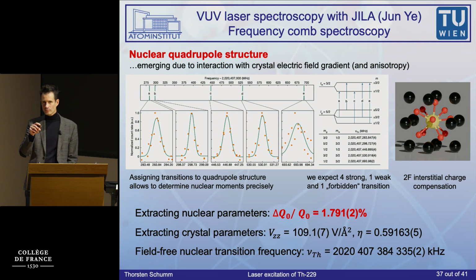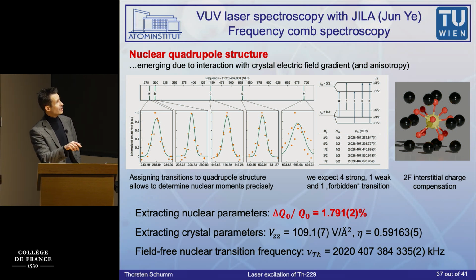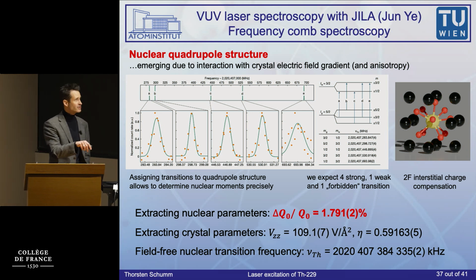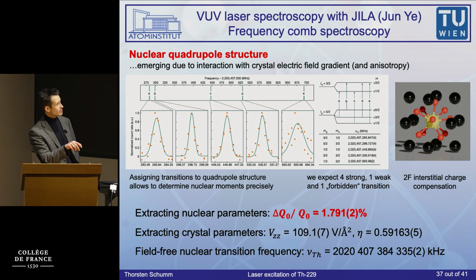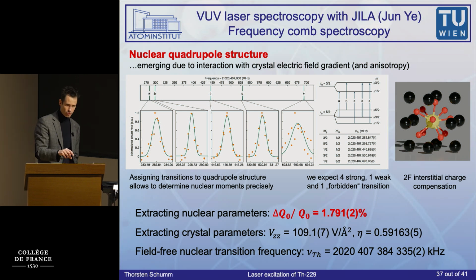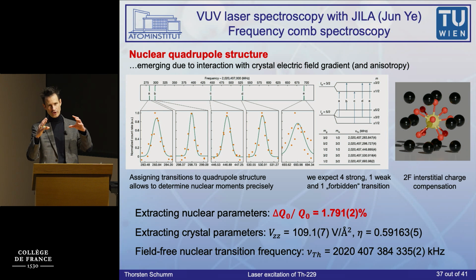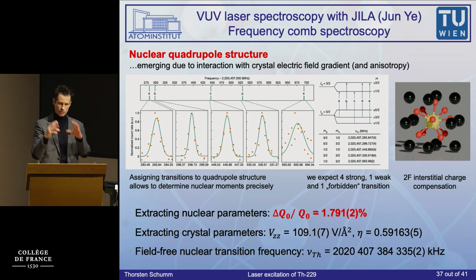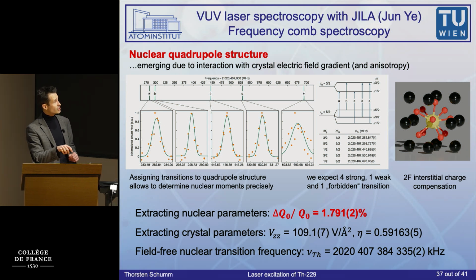And now comes the moment when we can actually use precision laser spectroscopy to learn something about nuclear physics, because these level splittings are determined by the electric field gradient in the material and the nuclear quadrupole moment, okay? And there are 5 lines. This system is mathematically overdetermined, so we can actually extract all of these numbers. So we can extract the nuclear quadrupole moment. We can even extract the change of nuclear quadrupole moment, which refers to a change in deformation of the nucleus when it goes from the ground state to the first excited state, which is on the 2% level, but with the accuracy we now have, we can do this.